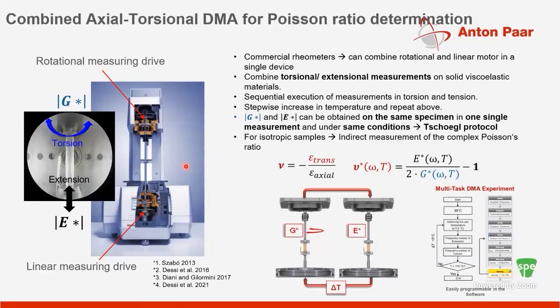And now, in turn, recently we have developed this, where you can actually do this measurement. You can set up a multitask experiment where you can now measure G and E at the same temperature on the same sample without changing it.